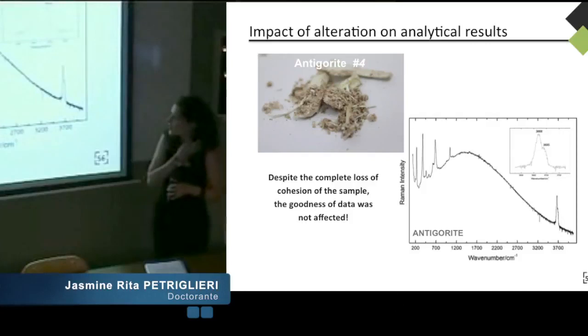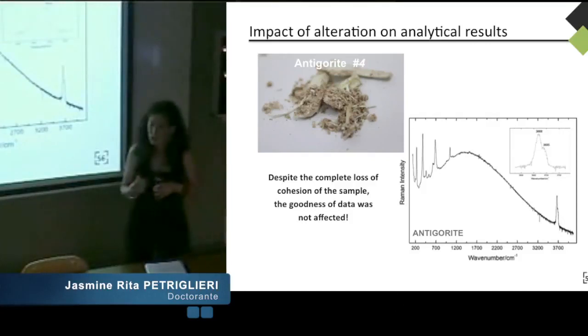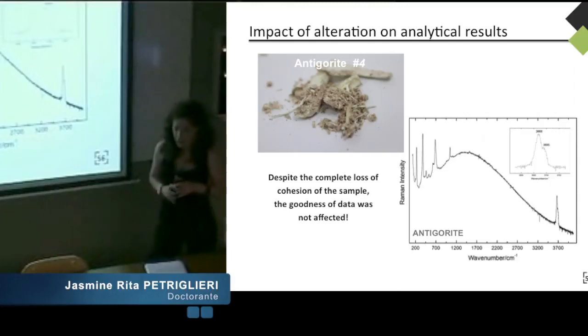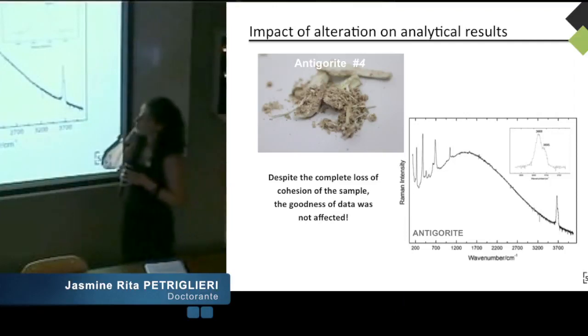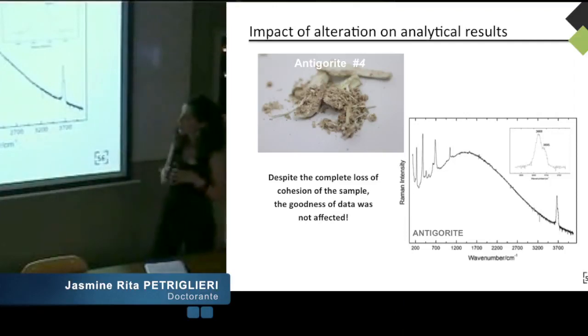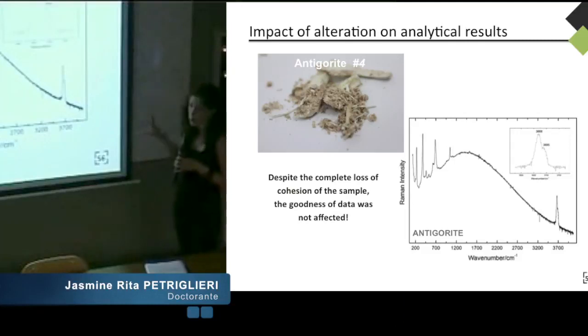Further analyses were realized on the most altered samples in order to evaluate the goodness of data compared to the alteration. As clearly evident in the picture, despite the complete loss of cohesion of the sample, the goodness of data was not affected. The portable Raman allowed us to identify, in this case, an antigorite phase.